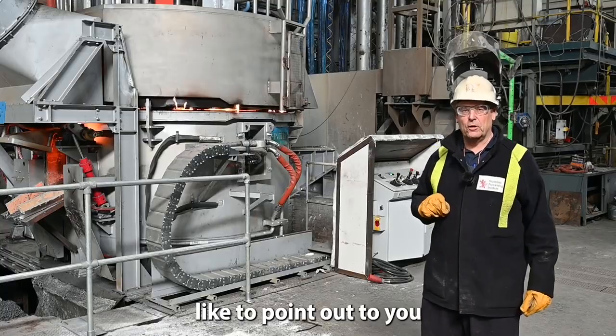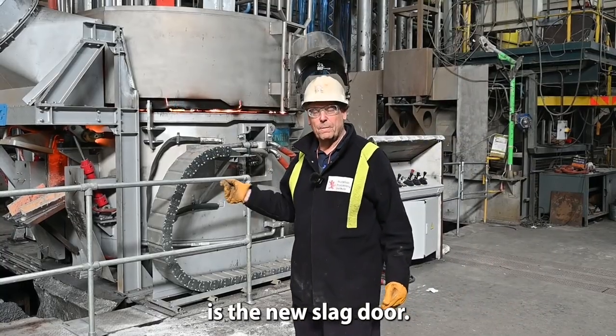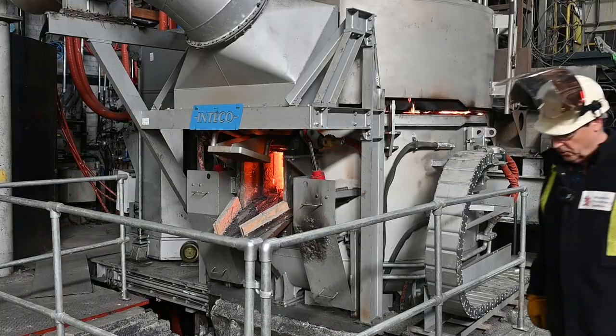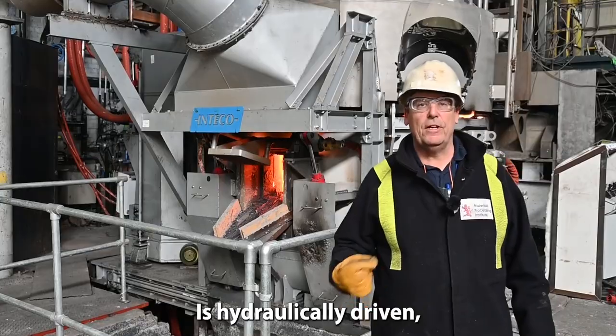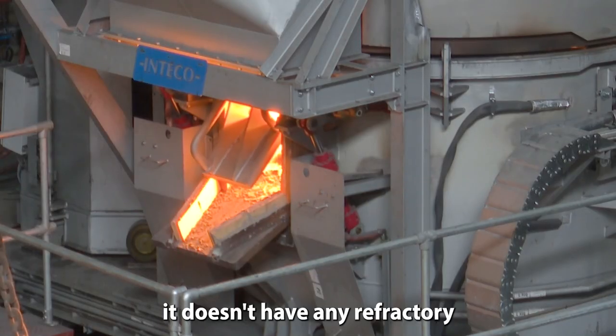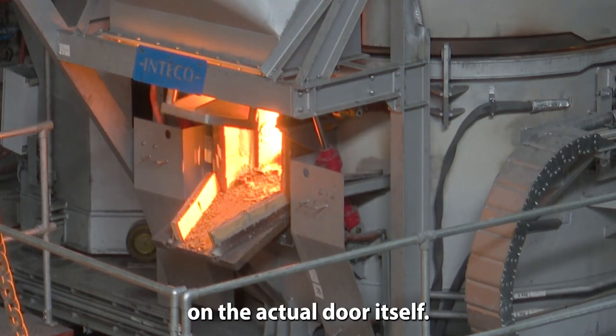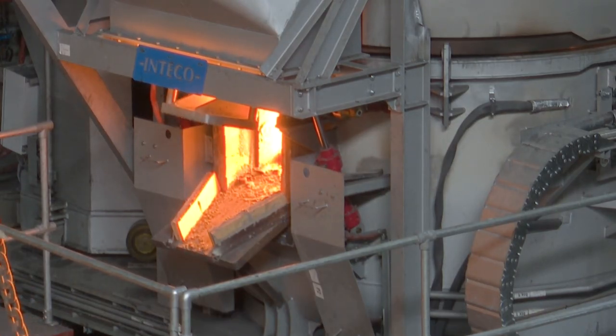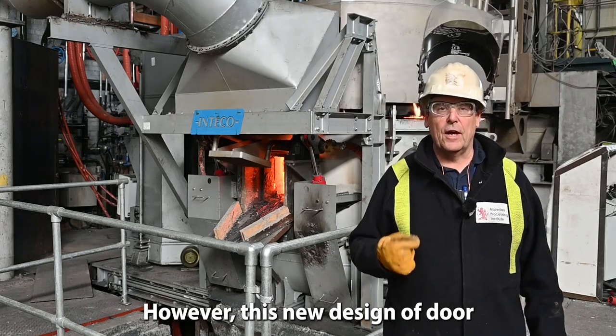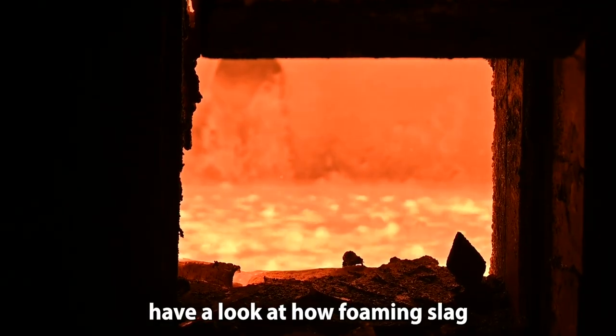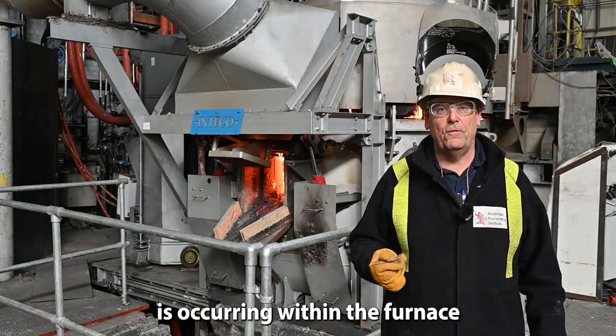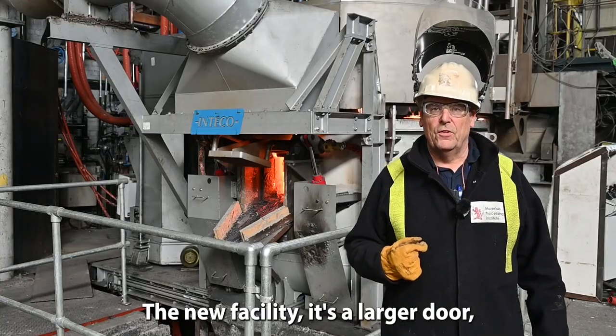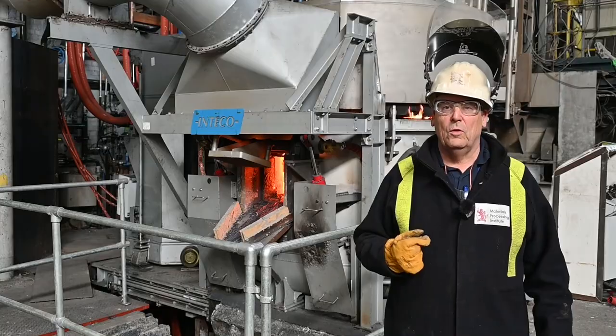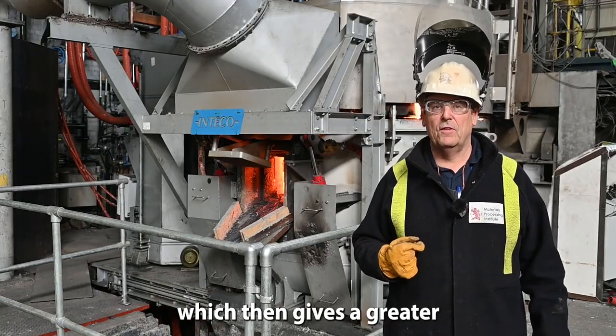Some of the other features I'd like to point out to you is the new slag door. The new slag door is hydraulically driven, and interestingly it doesn't have any refractory on the actual door itself. It is just a water-cooled steel plate. However, this new design of door allows us greater access to have a look at the arcs actually happening, and have a look at how foaming slag is occurring within the furnace when we're using the jet box. This new facility, it's a larger door, more vertically than horizontal, which then gives a greater field of vision.